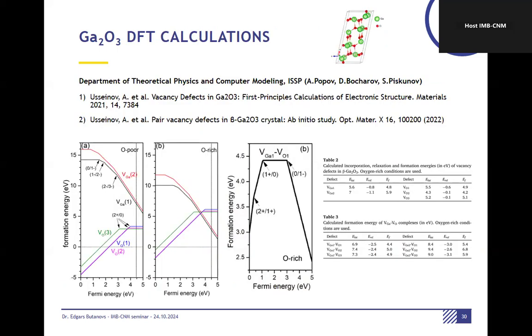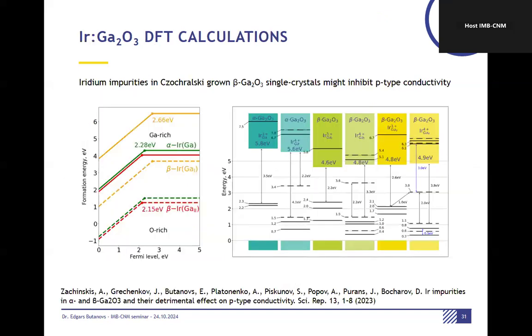In parallel, what we don't do, but what our colleagues from our institute do, we have a very strong theoretical group with DFT calculations. So in the initial stages of the project, back in the days, these are results from 2021, 22, when gallium oxide defects were not explored that much. They studied a lot of different types of monoclinic defects, mainly vacancies, oxygen vacancies, some interstitials, some nice papers, very well cited, from our colleagues.